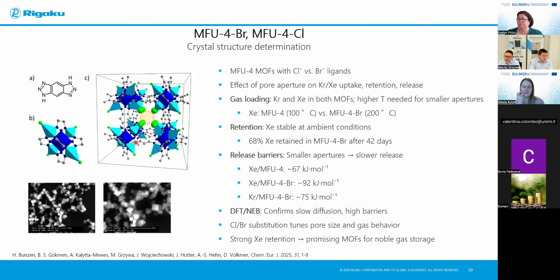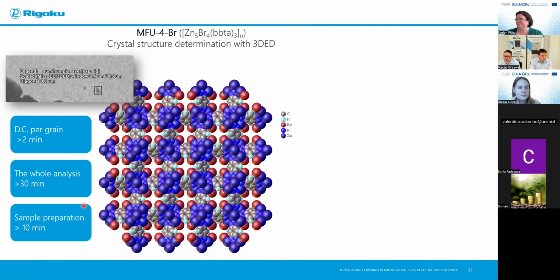In this case, MFU-4 bromide and chloride crystallize in the shape of very small submicron crystals, and it was not possible to use such a crystal for single crystal analysis. And in this case, electron diffraction was applied for data collection. Yes, and again, I saved you a picture of the grain I selected to solve the structure.